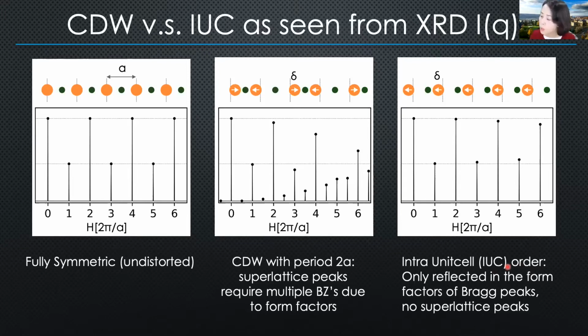Intra-unit cell order is only reflected in the form factor. So in this example, we have all the orange atoms being displaced in one direction. Now with this, the symmetry is lowered, but the unit cell size has not changed. So you don't see any new peaks, but you see the form factor effect.